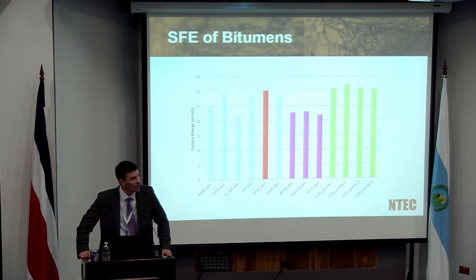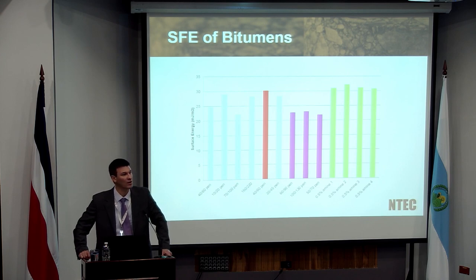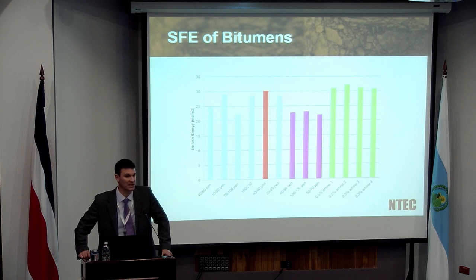As I said to you before, there are differences, but they're not massive, so you could end up with a surface energy value of about 25, and that could range up to about 30, so it's not a massive difference. It is interesting to note, though, if you look on the green four lines on the right-hand side, these were the same binders that we had used in turquoise on the left, but we had added an anti-stripping agent to the actual bitumen. So we've tried to artificially improve the resistance to stripping or to moisture damage of that particular binder by adding an anti-stripping agent at about 0.5%, so not a massive amount of material, using an amine system.